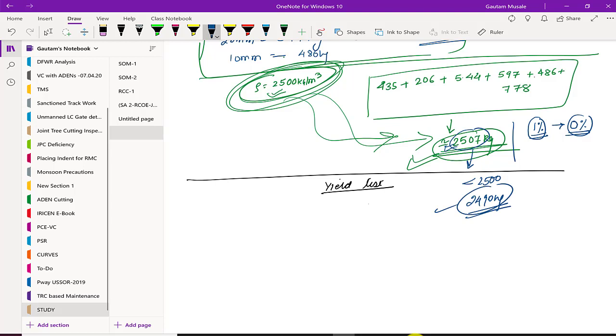I have already tried this, because when I did this trial, the IS code 2019 version was not released. So I adopted the older 2009 version, wherein there was no air entrainment clause. So I ignored it, and I observed that my density was lesser than required. My density was 2490, but the basic minimum density of concrete should be 2500.